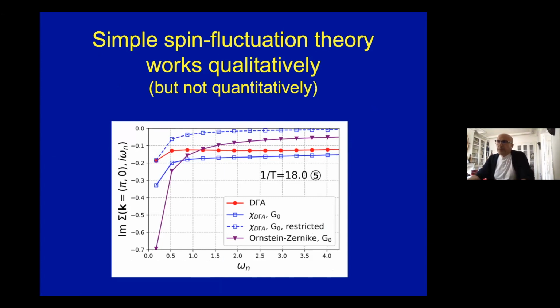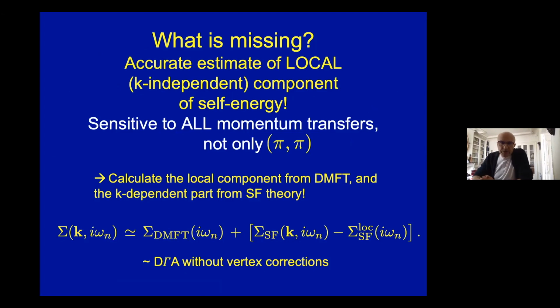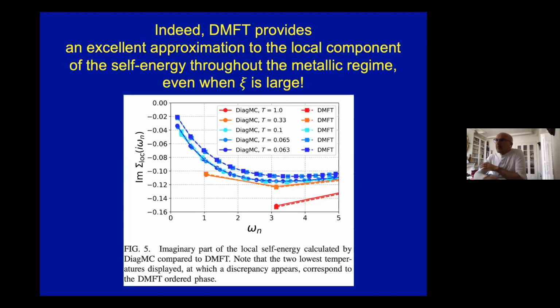And the reason can be understood by noting that the spin fluctuation calculation does a very poor job at capturing the overall local component of the self-energy, which, as you would guess from the speaker giving this talk, is actually very well given by DMFT, surprisingly. Actually, it turns out that throughout the metallic regime, the single-site dynamical mean field theory approximation does an excellent job of capturing the local part of the self-energy, even though the correlation length can reach values of order 10 lattice spacings.